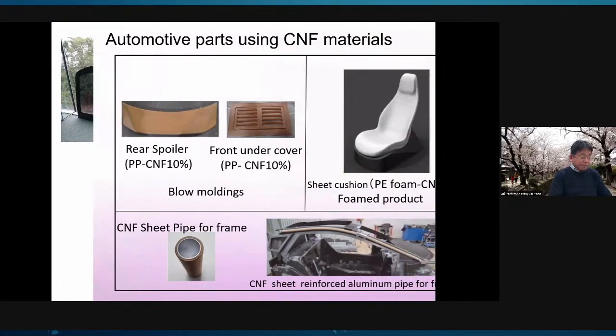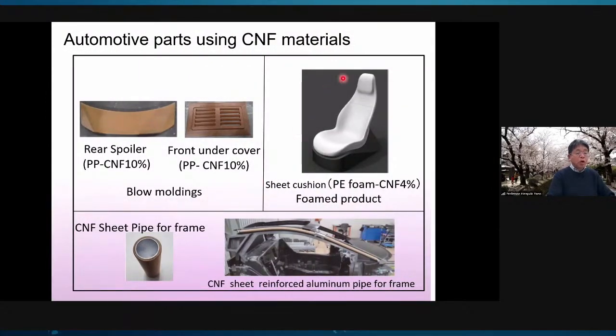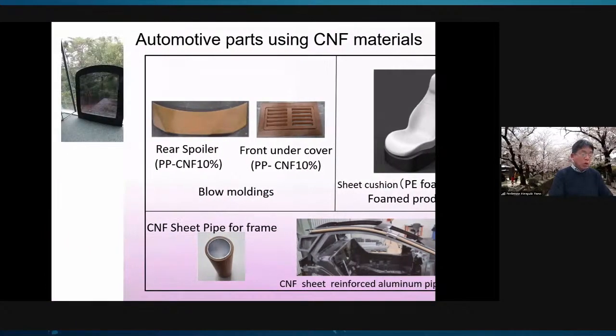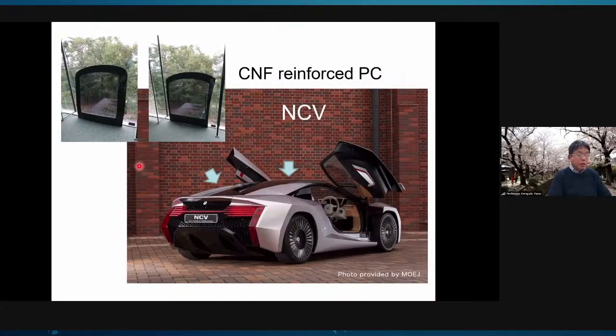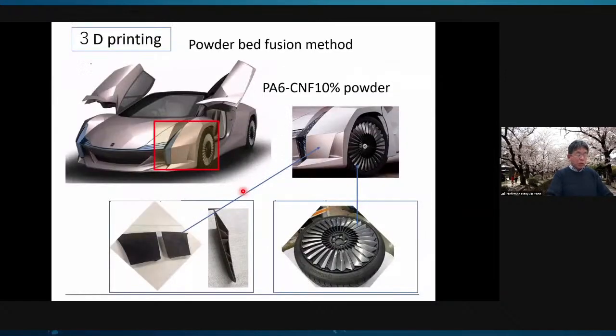And the seat cushion is made of foam CNF polyethylene. CNF sheet pipe is applied for the frame of NCV. Optically transparent CNF reinforced polycarbonate is applied for the roof, rear windows, and back door of NCV. We developed 3D printing technology in this project. The powder bed fusion method, PBF method, was applied for 3D printing fabrication using CNF reinforced polyamide 6 powders.